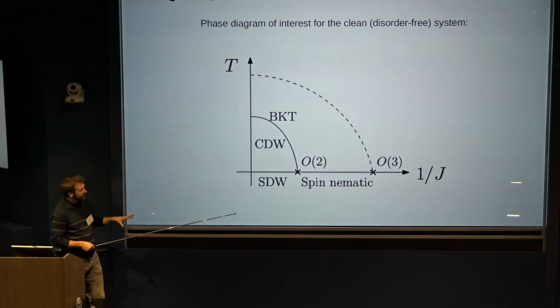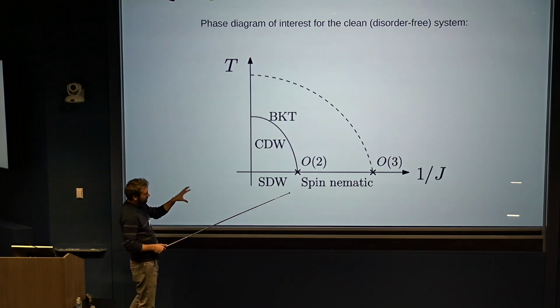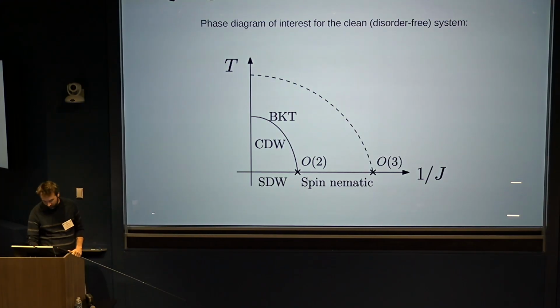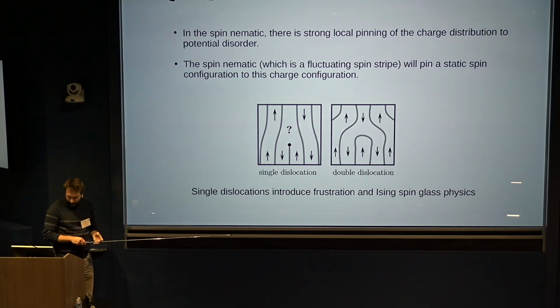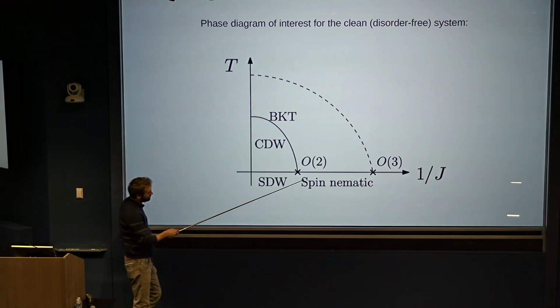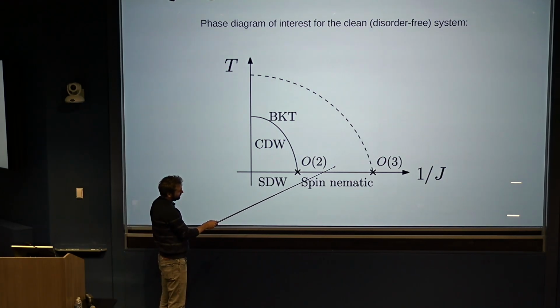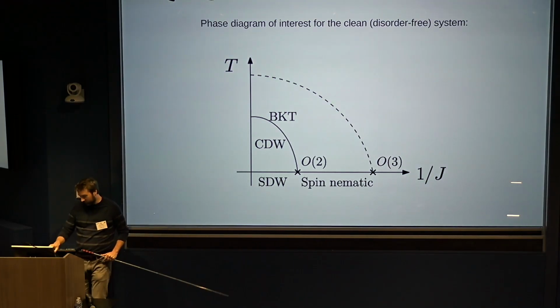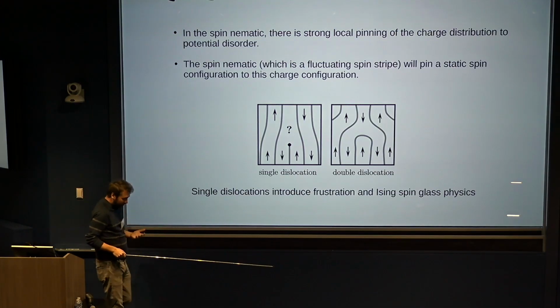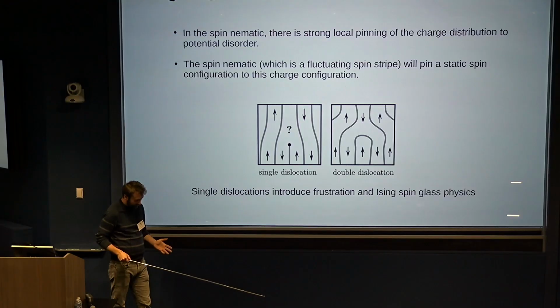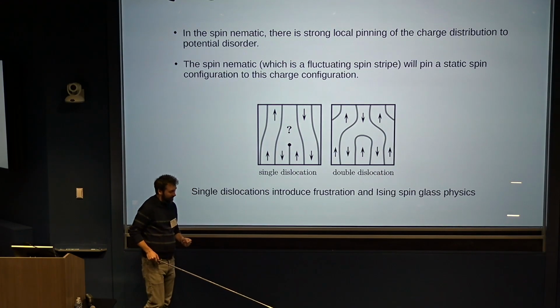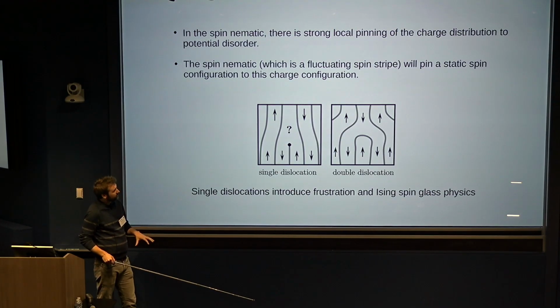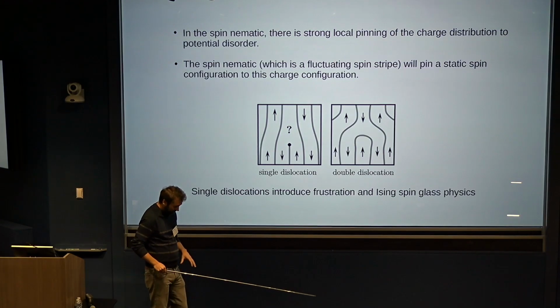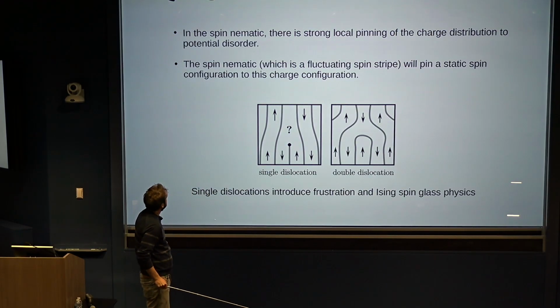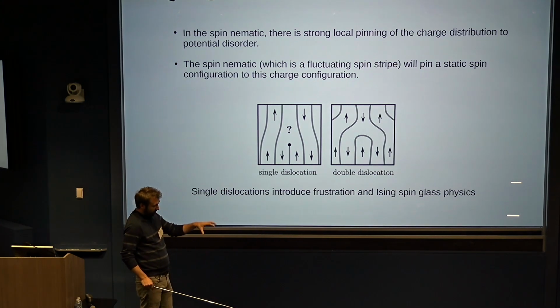Okay, but now I want to take this phase diagram and add on top of this conventional doping-induced potential disorder. Okay, what will happen? The main thing I want to discuss is what happens to the spin nematic as you now add potential disorder. Well, the correct way to think about the spin nematic is that it's really disordered spin stripes. It's really disordered by charge fluctuations. And so once you quench the charge fluctuations with a random potential, and you pin a particular inhomogeneous charge distribution, the magnetism should come back, and you will pin a magnetic order to this charge configuration.